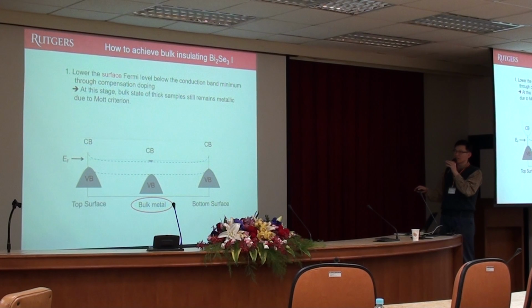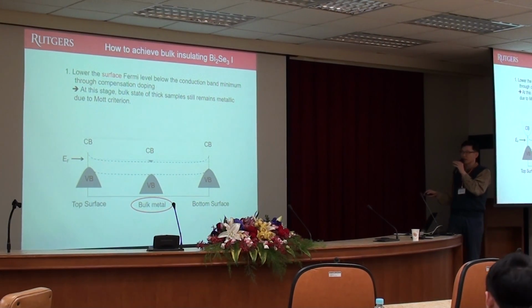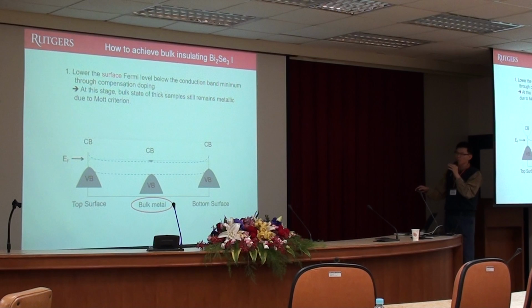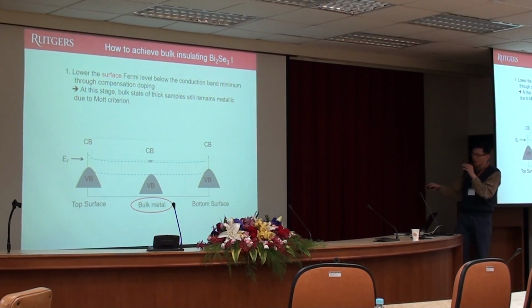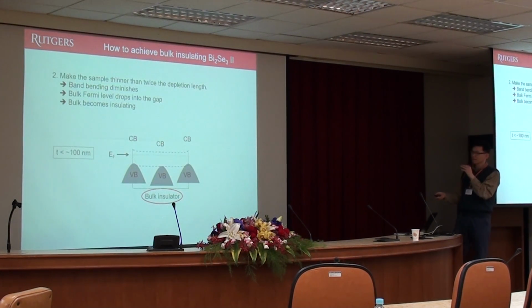On the surface you can have downward band bending or upward band bending. But let's say you are able to achieve upward band bending, then as we know, inside the material it is all metallic. This is the Fermi level, but at the surface you have upward band bending. Now, you make the sample thin. If you make them thinner than the depletion length, then energetically the band bending cannot be maintained beyond a certain level, so the Fermi level should pop down and it will become insulating.